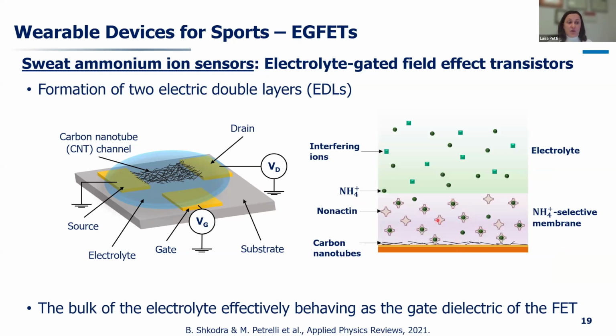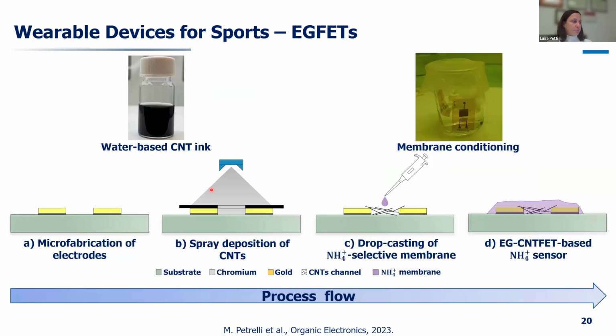The interesting part is really also the membrane, because if we now use an ionophore, so an ion selective membrane, in this case for ammonium ion, because that's what we're interested in, what we see is that from all the interfering ions that we can have in the sweat, only ammonium ion is able to diffuse and enter and get in touch with the carbon nanotubes and lead to a variation in the transistor current that can be read and correlated to the difference in concentration of ammonium ion.